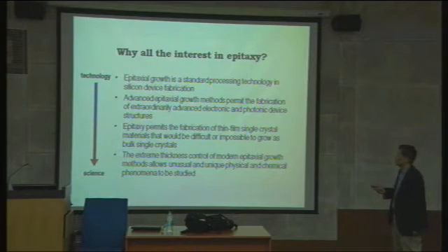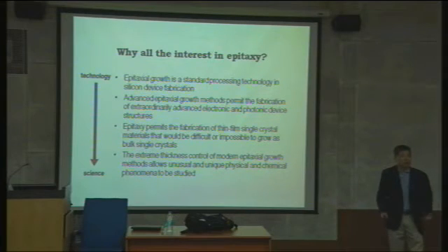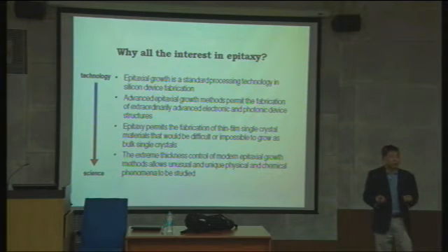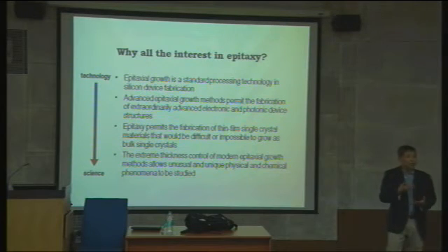Epitaxial growth is a standard processing technology in silicon device fabrication. So, for example, when you look at your microchips, and you have layers on top, you grow p-n junctions and those things. It's basically the same kind of p-n junction. And then on top of it, you grow another layer of germanium. And you have a lot of high electron mobility devices. They have heteroepitaxy in germanium and silicon germanium, and then sometimes gallium arsenide, aluminum gallium arsenide quantum structures for lasers. They all use a heteroepitaxial approach in semiconductors, and that's technologically very important.